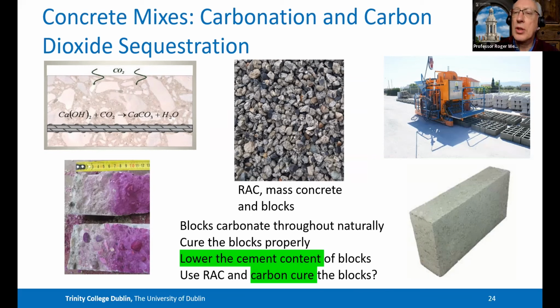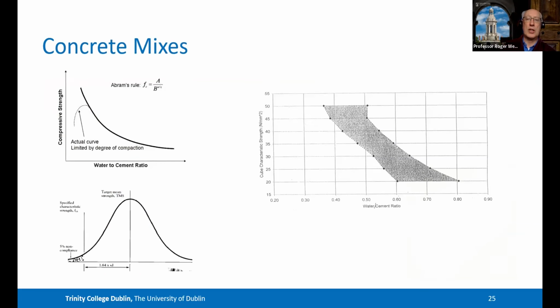But I just make a final point here on this. The concrete blocks, when we pour them, and we've observed this, if you don't cure the concrete blocks, then you rely on an extra bit of cement in order to get them to harden and develop their strength. And it's not a very high strength that's required. Typically, nowadays, anything above 7.5 megapascals. So I wonder whether or not, as some manufacturers clearly do, there's scope for using less cement, but curing it much better so that you attain the necessary strength, and indeed even use recycled aggregates in a block, given that it has a specific requirement for strength, but it should be possible to meet that requirement by optimizing the cement content. Just a thought.